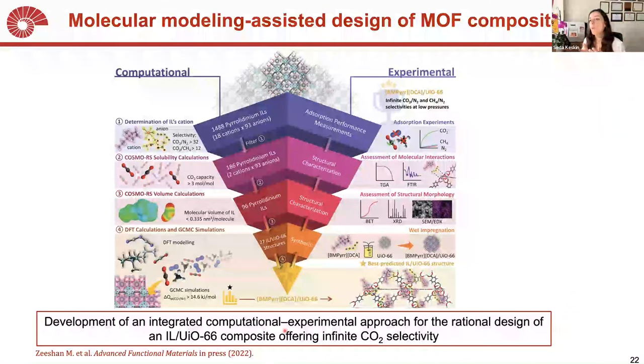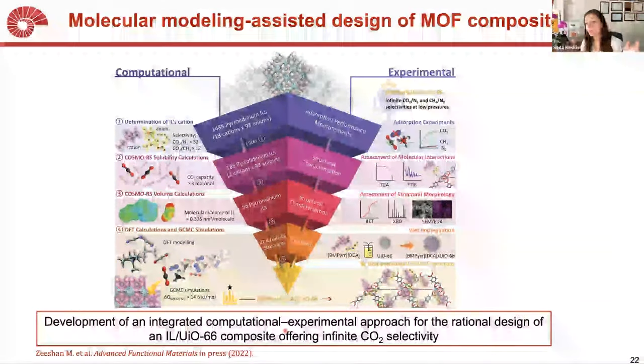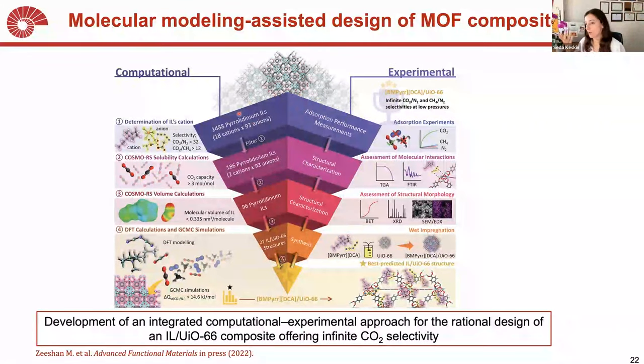So we said, let's combine this high throughput computational screening approach with the experimental work to find a new material. So we started with a small number of ionic liquids, around 1,000. And then we did some DFT calculations, COSMO-RS calculations to find the ionic liquids that have high solubility for CO2. And then we defined a few types of composites to study with the GCMC simulations and identified the composite showing the highest selectivity for CO2 nitrogen separation. So the ionic liquid was chosen as a result of this computation, and the MOF was already set. We specifically wanted to study a robust and large pore material, UiO-66.